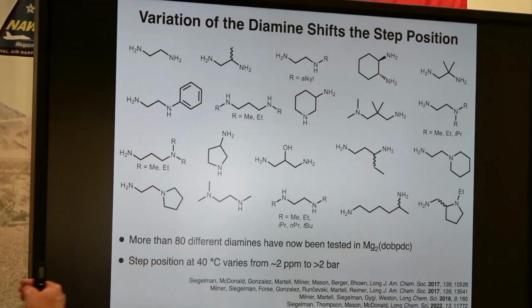And at, say, 40 degrees C, you can move the step anywhere from very low pressures, 2 parts per million, where you're capturing very deeply from air, to much higher pressures, out past 2 bar, which might be of use for high pressure separation.